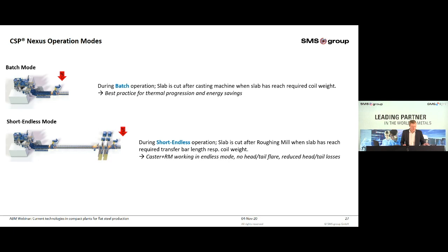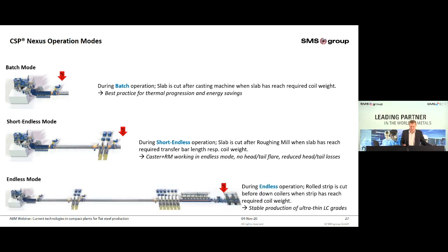In endless operation, the strip is cut right before the downcoiler with a high-speed shear. The entire plant will work in endless operation. This will increase rolling stability of ultra-thin, low-carbon grades. The Nexus plant can produce low-carbon grades in endless without an additional induction heating, which lowers the overall OPEX. As you can see, 3 modes are possible with the CSP Nexus plant. Each mode has some pros and some cons. At the end, the operator can choose the most beneficial mode for each product.